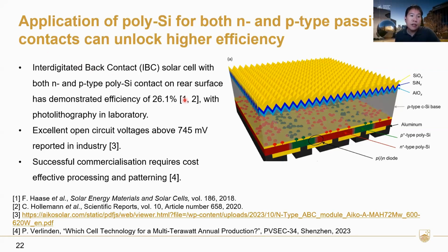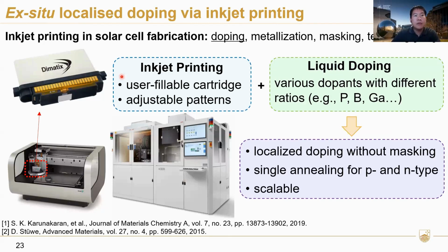polysilicon. So indeed, the group at ISFH has demonstrated, I believe it's still the world's highest efficiency of a laboratory cell using an IBC polysilicon solar cell. In the industry, there's also significant interest in demonstrating back contact solar cells, with ISC Konstanz already reporting an open circuit voltage of about 745 millivolts. This is in industry, in large area devices. But it is generally accepted that successful commercialization of the technology requires cost-effective processing, and a big part of it is patterning. So here's where we think inkjet printing can be useful.